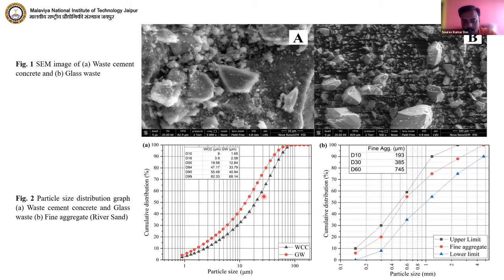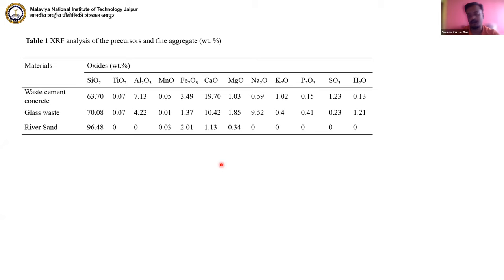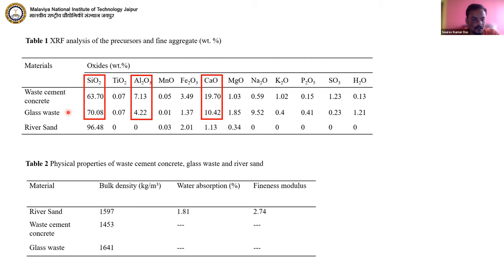So these are the XRF analysis results to get the oxide content of the different wastes, that is waste cement concrete and glass waste. When you talk about geopolymer, the important thing is the amount of silicon dioxide, aluminum oxide, and calcium oxide present. Here you can see that both glass waste and waste cement concrete have a good amount of calcium oxide, which is a good sign, so that we can achieve a moderate amount of compressive strength at ambient temperature. That is one of the reasons why I chose these two wastes, because my focus is on producing geopolymer at ambient temperature. And these are some of the physical properties of the materials utilized here.